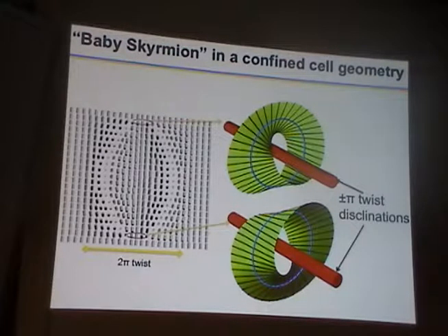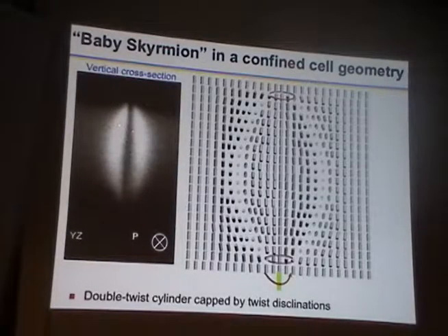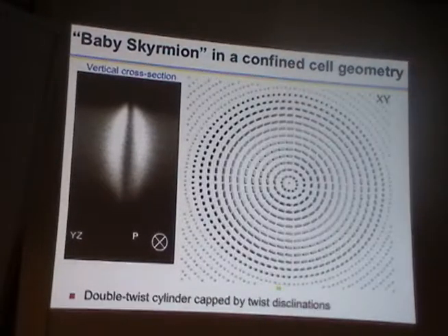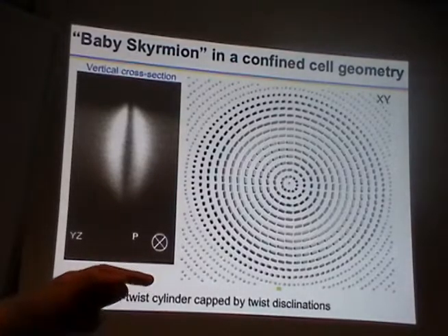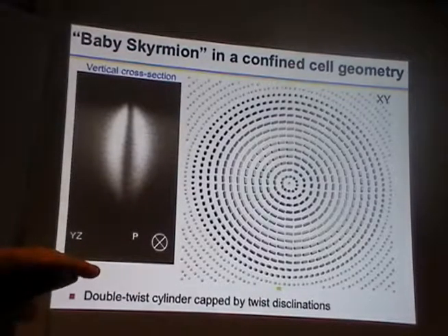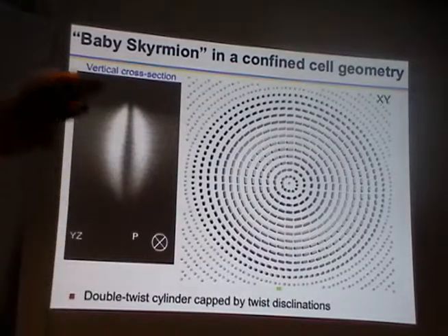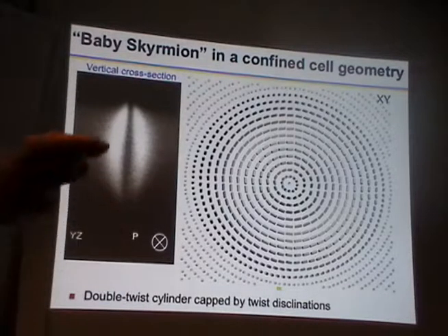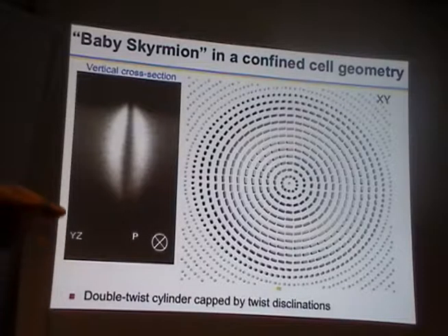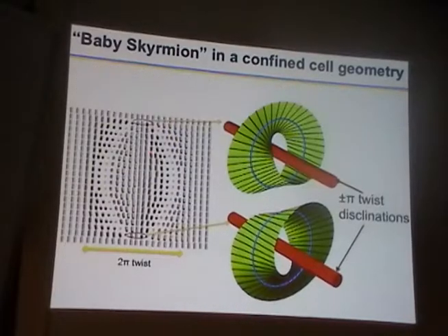They are experimental data. So essentially, based on images of this kind, many images of this kind, you can reconstruct what happens with director field, say in the middle of the plane, and then because we have resolution not only in the plane of the sample but also across the sample thickness, you can probe what happens with director field as you come close to substrate. And so you can note that we do meet the surface boundary conditions, right? And that happens because of presence of those disclination loops.